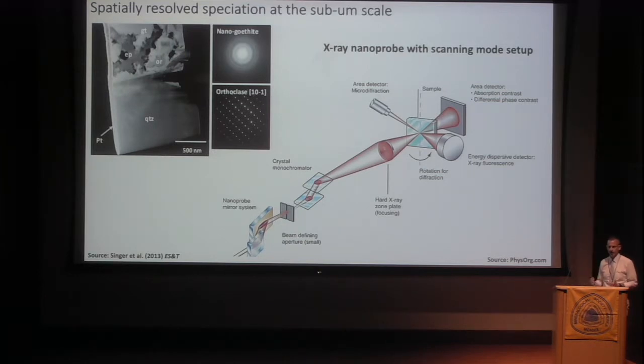but trying to understand the fate of, say, nutrients or contaminants within these nano regions, or at least certainly sub-micrometer regions, is a little bit more tricky. One thing that might help is the development over the last few years of X-ray nanoprobes that can be run in scanning mode that don't necessarily get to atomic or true nanometer scale resolution, but do open up the possibility of tens or hundreds of nanometers of spatially located chemical information, where we could say something about, well, if there's arsenic or uranium moving through these materials, to actually get down to that sub-micrometer scale and say something about speciation and distribution.